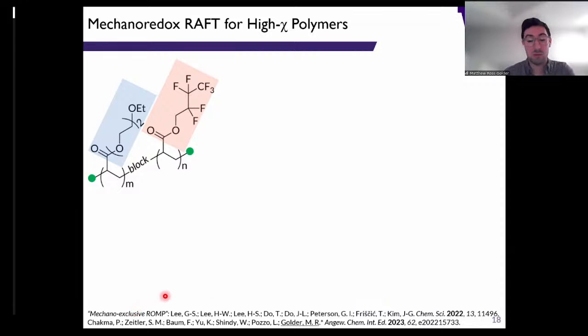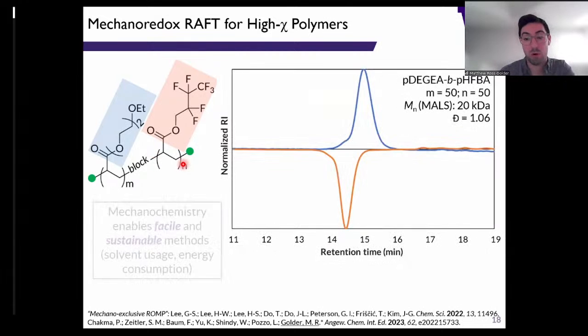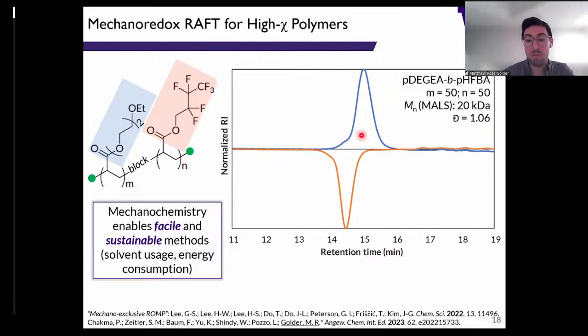This was recently shown in this nice ChemSci paper from Tomislav and J.-G. Kim, where using some of these same principles, we thought that we could access this semi-fluorinated polymer that contains both the hydrophilic building block here in blue and this semi-fluorinated block here in orange. You can see the same type of peak-to-peak transformation here. The upside down peak is just due to the fact that the refractive index of this material is lower than that of our mobile phase on our HPLC.